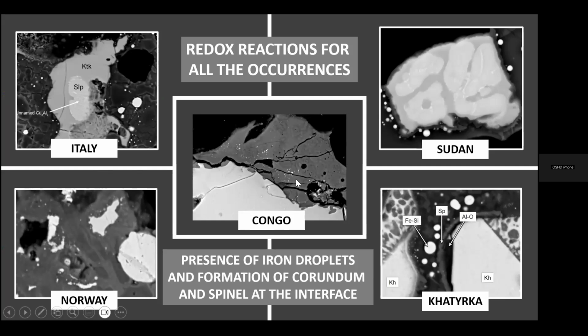So you can see that you have the metallic droplets, and then you have the new generation of spinel. I think that the image of the Khatyrka here is really impressive. So the strongly reducing conditions are able to reduce the iron in the silicate, and in this case, also part of the silicon, to form iron silicides. And then you have a new generation of corundum and a new generation of spinel, and very impressive.